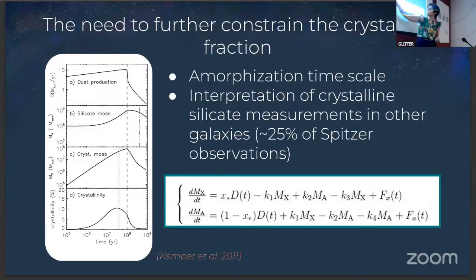This is an important diagnostic tool because in starburst galaxies, and we have done this calculation, you can actually calculate that, because freshly ejected stellar material does contain crystalline material. So initially the interstellar medium is somewhat crystalline, and over time it becomes more amorphous as the starburst dies down. Here we have dust production by the stars in the starburst. We have the silicate mass in the interstellar medium going up, the crystalline silicate mass going up, and here we have the ratio of the crystalline and the amorphous silicates giving the crystallinity, and it can reach about 10%. These calculations were done in response to the identification of crystalline silicates in the starburst galaxies observed with Spitzer.